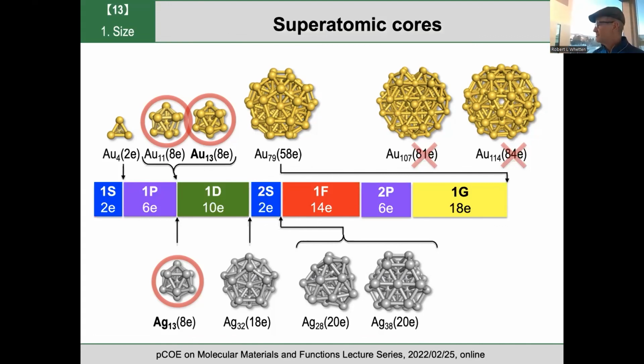How could they do this? Because the moment this is exposed to an oxidizing environment, it's a strong electron donor, like I said. But anyway, I hold up that example. They characterized it by MALDI mass spectrometry. It looks very good. And it's a reminder that under the strongly reducing conditions under which we all like to generate our selected clusters, the charge state can be quite a bit more negative than the products that we finally store and characterize.